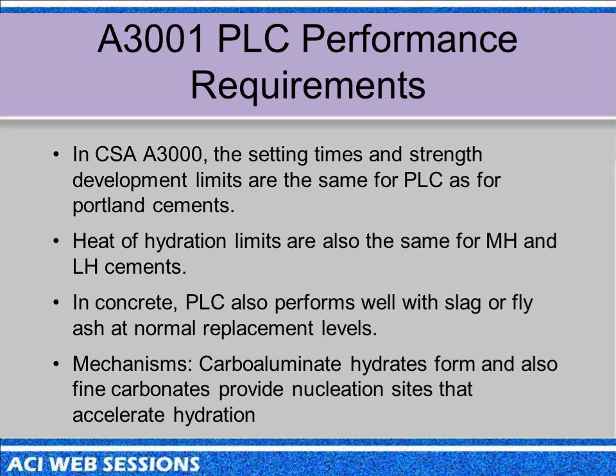So as I said before, the standard says the setting times and strength are the same with Portland-limestone cements of the respective types as Portland cements. For moderate heat or low heat cements, it doesn't change anything in terms of the performance requirement, the heat of hydration limits. And as I said, it works very well with slag or fly ash at normal replacement levels.